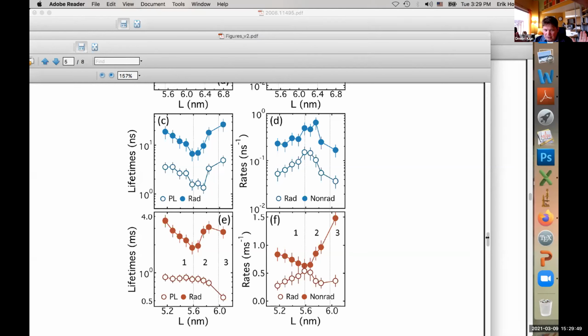So we should consider either a band of slightly degenerate states of impurities, or I can offer this crazy idea of vacuum, if we forget about lead, filled with a high amount of manganese ions, and there will be a wave function spread over all manganese, same as a particle in a box. Or again, as a limiting case, I am not saying that we need to do the following numerical experiment, but we can consider a model where all lead is replaced by manganese, and I bet that the gap energy will be substantially lower.